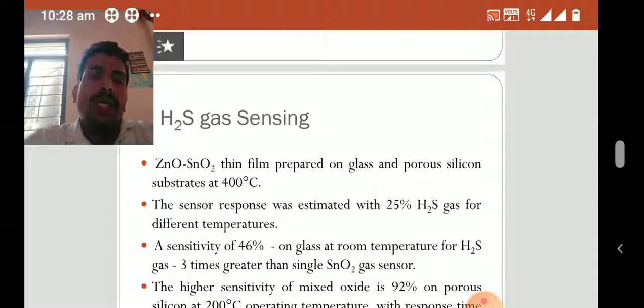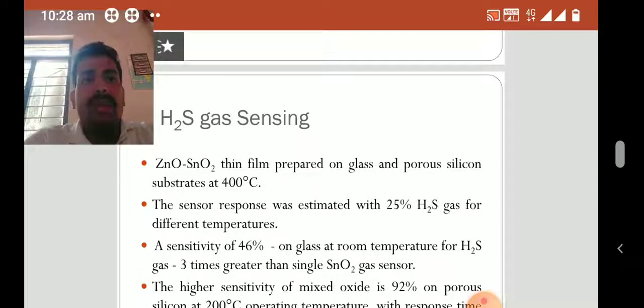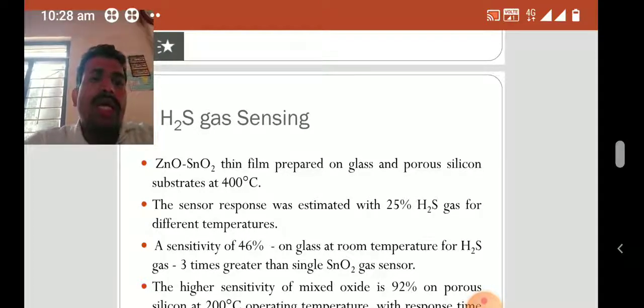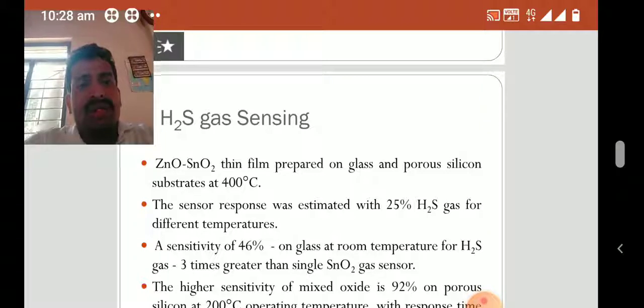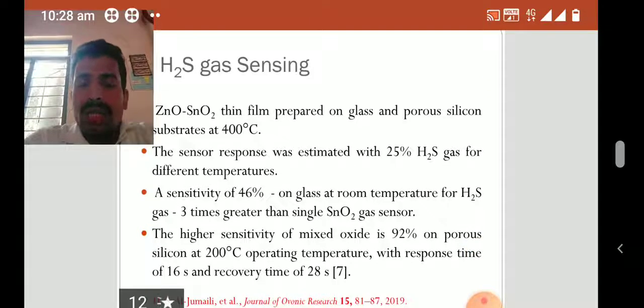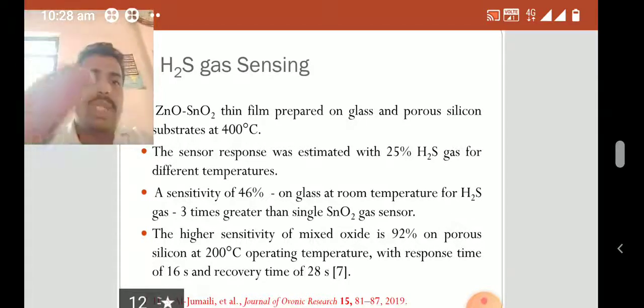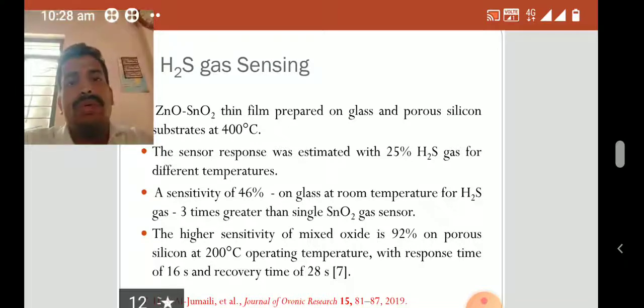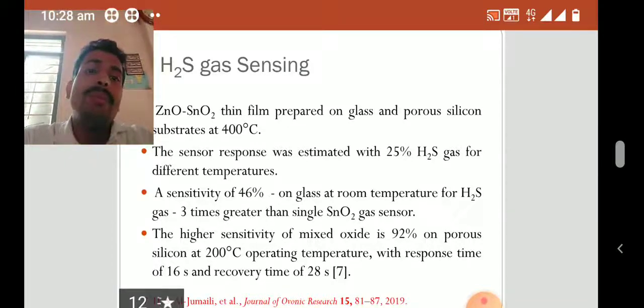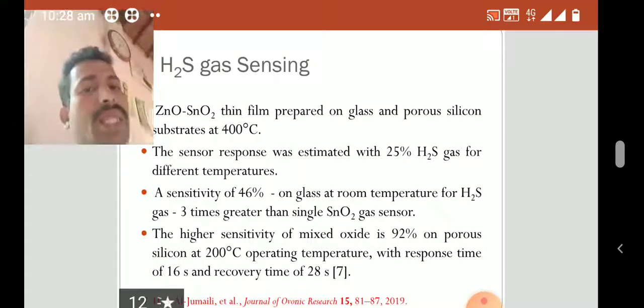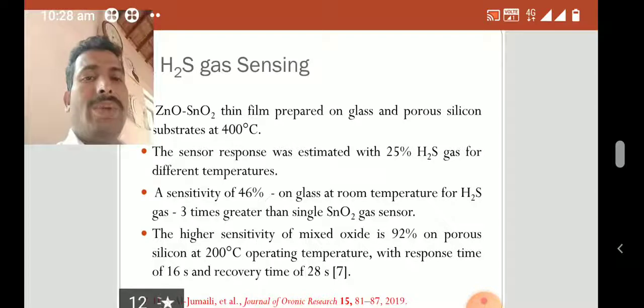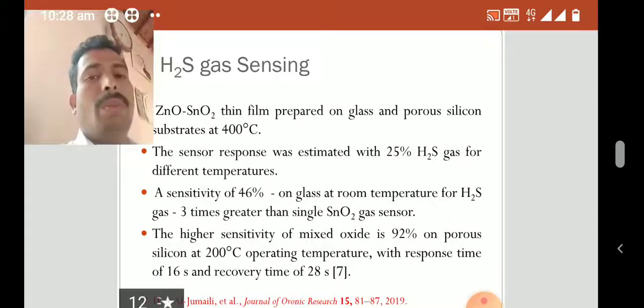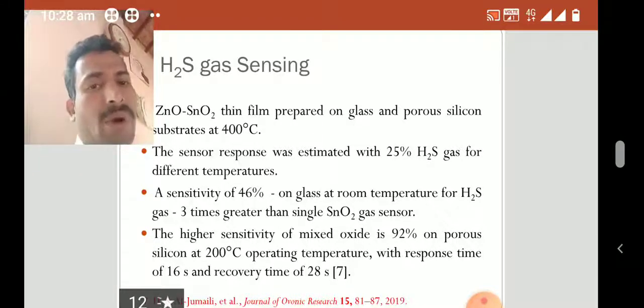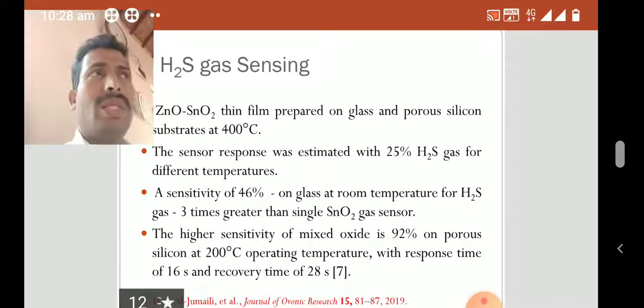Next, the study on hydrogen sulfide gas sensing. Zinc oxide tin oxide thin film was prepared on glass and porous silicon substrates at 400 degrees Celsius. The sensor response was estimated with 25% hydrogen sulfide gas at different temperatures. A sensitivity of 46% was observed on glass at room temperature for hydrogen sulfide gas, which was 3 times greater than the single tin oxide gas sensor. Here, the higher sensitivity of the mixed oxide is 92% on porous silicon at 200 degrees Celsius operating temperature, with response time of 16 seconds and recovery time of 28 seconds, which is a better result.